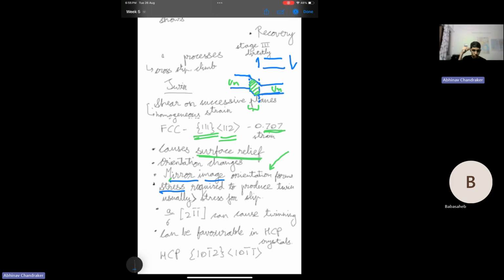Also, twinning is less common compared to slipping because the stress required for slip is usually much less than that required for twinning. But in special cases, mostly where slip is difficult and more stress is required, for example at lower temperatures where thermal energy is lesser, and in cases of high strain rates, where again due to thermal energy and diffusion being difficult at lower time scales, slip is difficult, and therefore twinning can occur. The stresses will become enough for twinning to occur. So in such cases, twinning may dominate, but in general, slip is more common, and more of the deformation tends to occur by slip than by twinning.